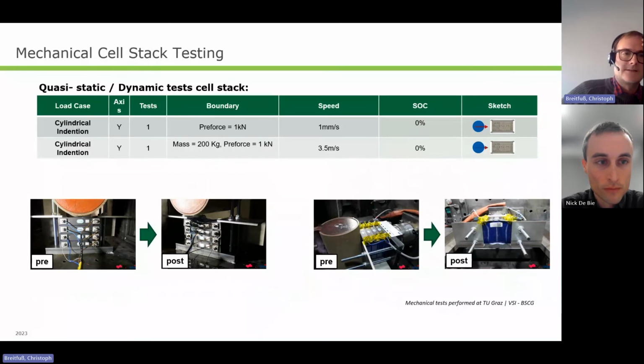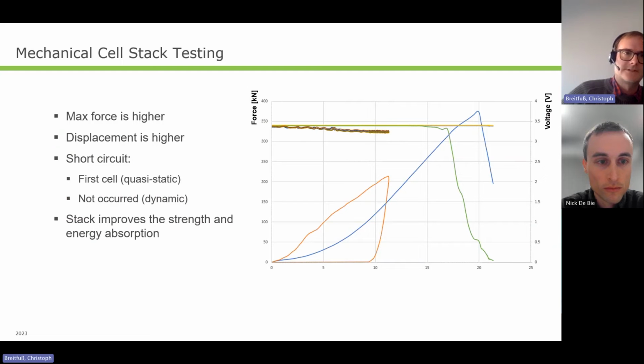Now we come to mechanical stack testing. We did quasi-static and dynamic stack tests. I will go right to the results. The results show phenomena very similar to the ones with the single cell, but there's a big difference. Compared to the single cell test, the maximum force and the displacement are much higher, which means that the stack improves the strength and energy absorption compared to a single cell, which is very positive.